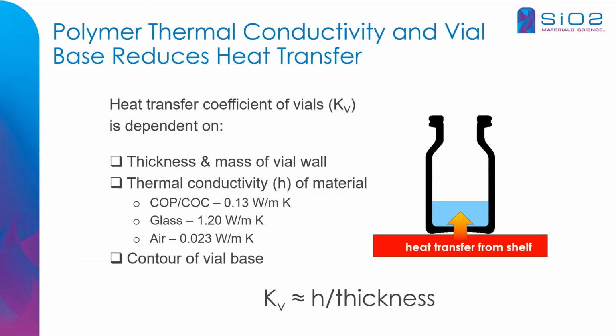I think one of the things that we noticed, and you might be thinking, is, hey, what about the lyo cycle, particularly when the heat transfer coefficient of plastic is much lower than glass. You can see an order of magnitude difference between cyclic olefin, COP, COC versus glass. But the heat transfer coefficient is only one aspect. The heat transfer is really driven by the coefficient and the thickness of the container, so variation in thickness also affects the heat transfer in the container.